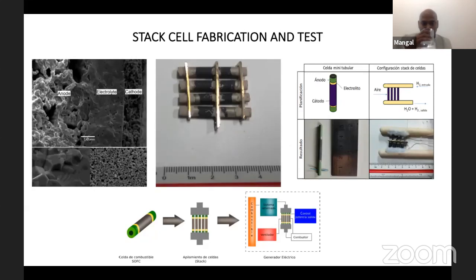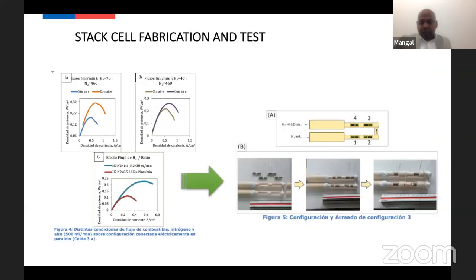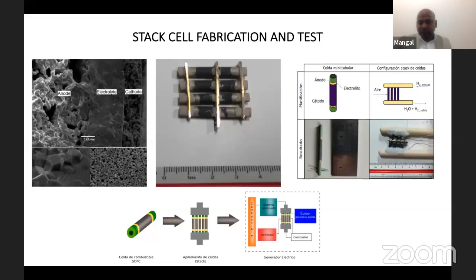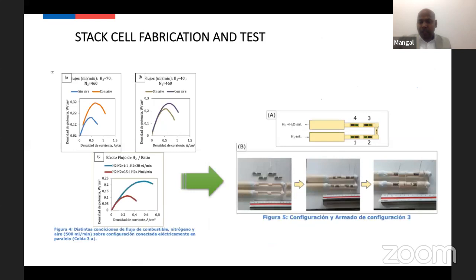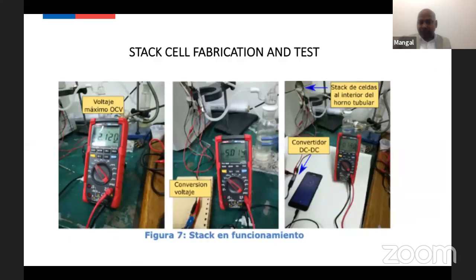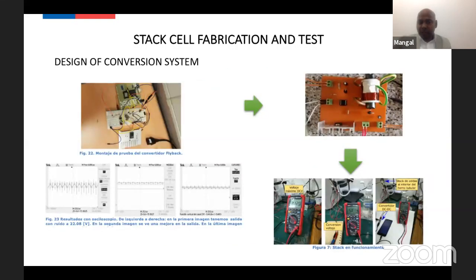So you see the microstructure of the tube. You see how porous the anode is, how dense the electrolyte is, and how porous the cathode is. So after making this stacking, we also think about series mode and also parallel mode. With this integration, we tested, and it really gives a good result when we use the converters to improve the efficiency, and not only integration, it adds more output when we use the converters.